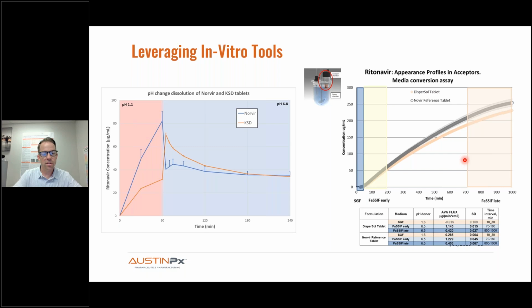So now at AustinPx, we really believe strongly in having numerous in vitro tools for establishing biopharmaceutical performance. So we look at various biorelevant dissolution methods and also combining that with transmembrane flux to get two different data sets to select formulations. So this is what you see on the screen. On the left, the donor side, a pH change, non-sink gastric to intestinal transfer dissolution system. So you see very different release profiles. Norvir releases extensively in acid and then precipitates after the pH change. Meanwhile, our formulation is enteric based, releases to a minimal extent in acid and then supersaturates in intestinal media.